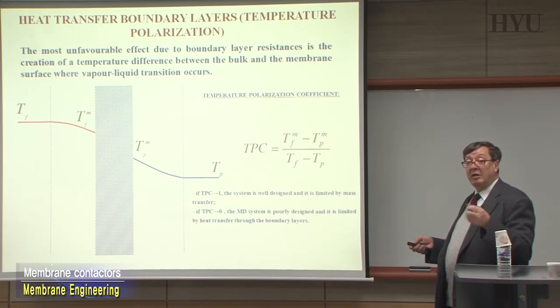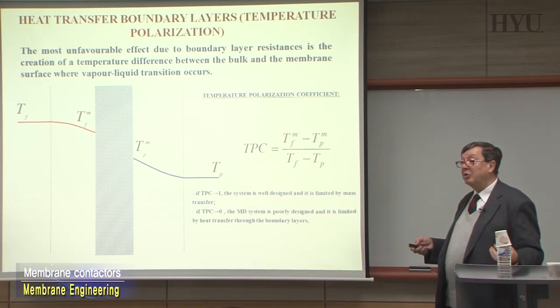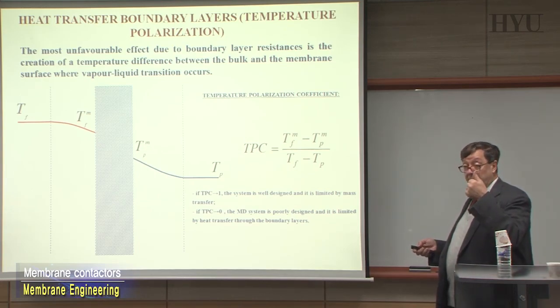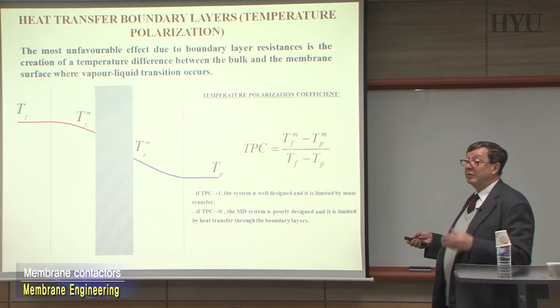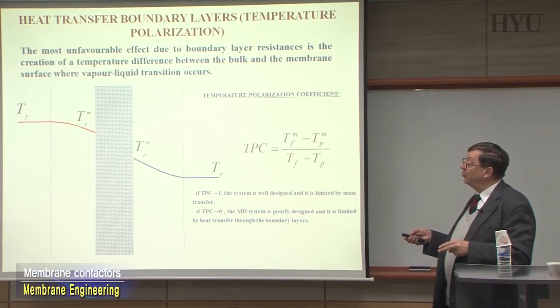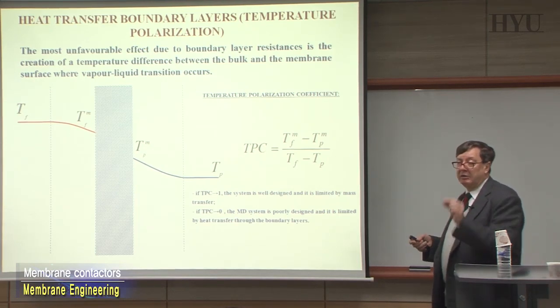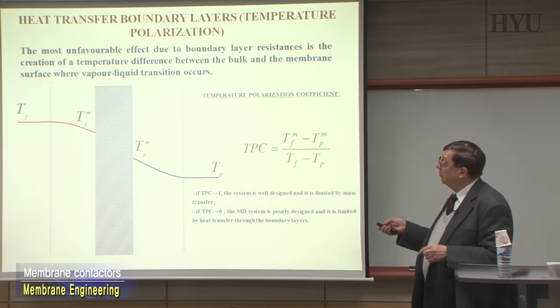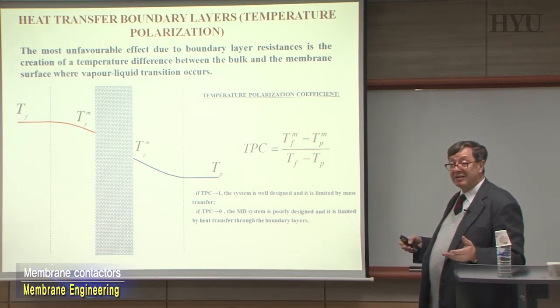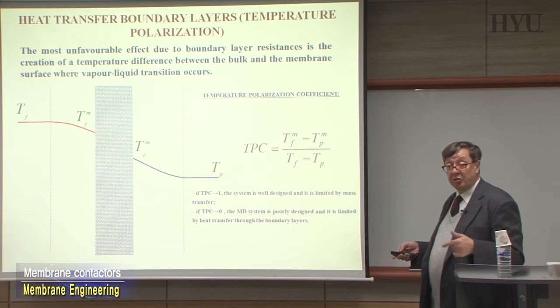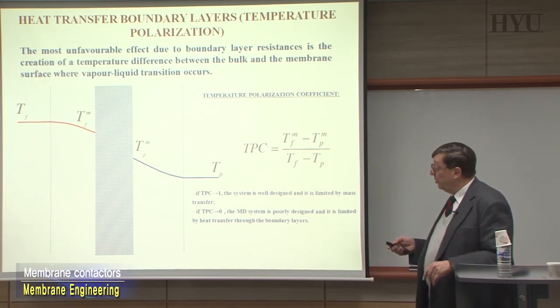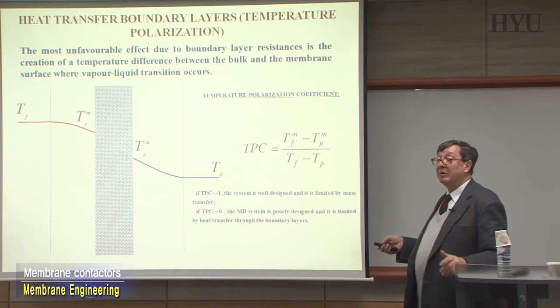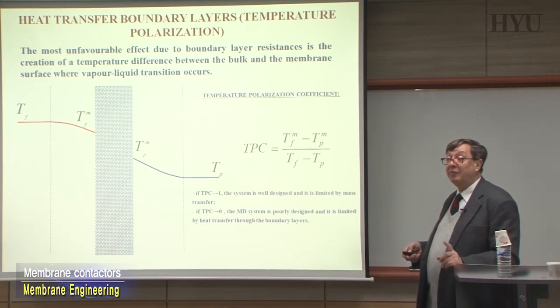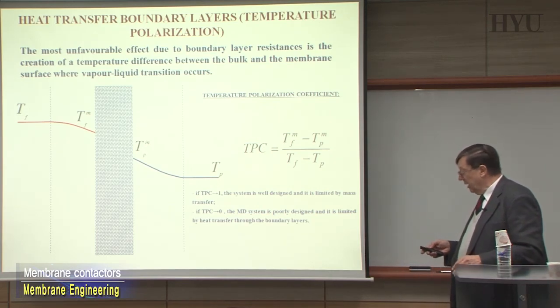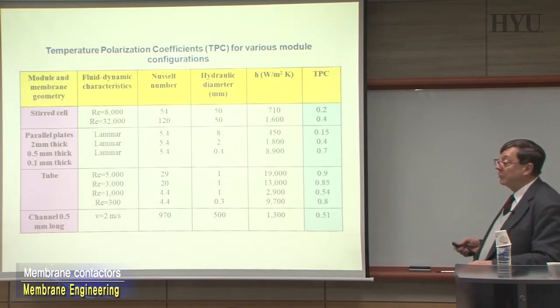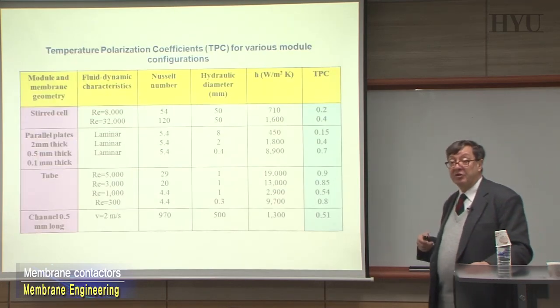So if you don't keep control of this temperature profile, you are decreasing two very important things. Point number one, you are decreasing the number of molecules that from liquid phase go into vapor phase. Second, you are decreasing the delta T necessary for moving these molecules across. Delta T can be very small because this is a porous system, so you don't have big resistance. However, it is a loss of driving force. So this phenomenon can kill membrane distillation completely if not well controlled. Exactly the same as what we discussed when we were discussing reverse osmosis.